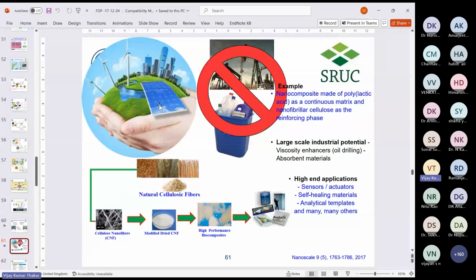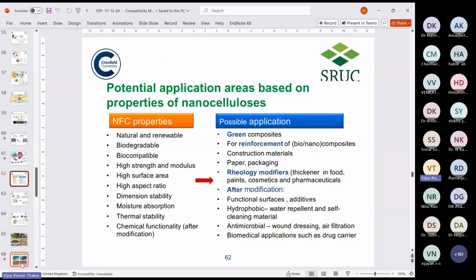Significant efforts are going on for development of wind turbines with the help of sustainable material, especially cellulosic nanofiber. These wind turbines are mainly made up of glass fiber as well as other synthetic fiber material. Obviously, we cannot completely replace the synthetic fiber composite, but we are trying to embed nanocellulose in a sandwich structure where we at least incorporate some sustainability, and at the end of their life cycle, these cellulosic nanomaterials embedded within the wind turbine blade can initiate the degradation process.